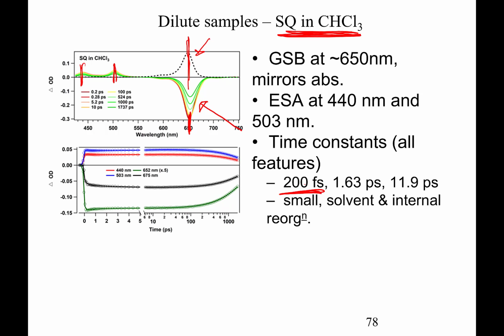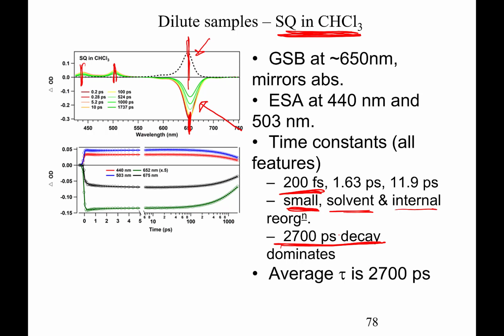We have small decay constants. They're also associated with solvent reorganization and internal reorganization of those molecules very quickly within the solvent lattice. They're not restrained in any particular position, so they can relax fairly quickly. We also see a very dominant 2.7 nanoseconds, 2700 picosecond decay that dominates for these materials, very similar to the fluorescence lifetime of, again, 2.7 nanoseconds for these materials.